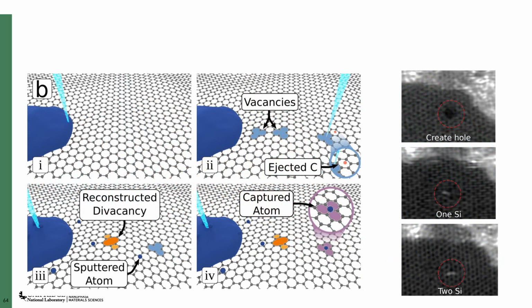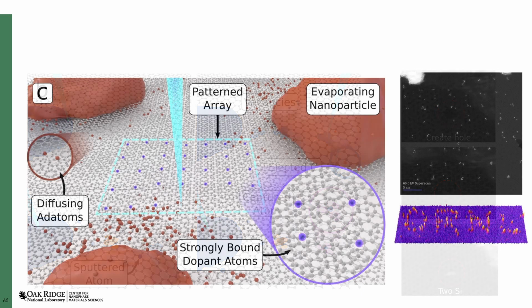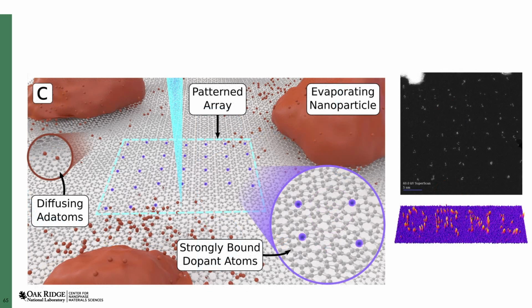We showed that this works for silicon and a long list of other elements. But it only works very close to the reservoir of source material, and we are using the E-beam to both damage the substrate and sputter atoms from the source material. If we use thermal evaporation, or atomization, it appears we can supply these atoms from a longer distance and start to perform automated patterning at the single atom scale.